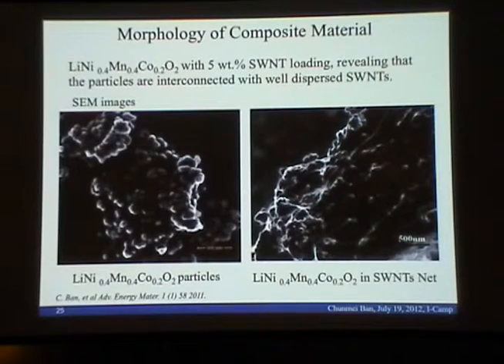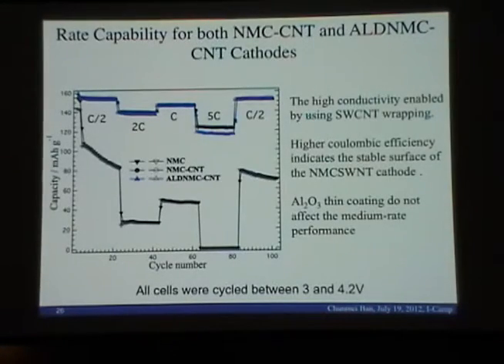This SEM image shows primary particles and finally combined with carbon nanotubes. And those nanotubes are very well dispersed into this particle structure. And finally, we found they have a chemical bonding between those particles and the carbon nanotubes. That further enhances the conductivity, especially the electron transfer on the surface, because the carbon nanotube is on the surface. And so this is the comparison of the effect of this carbon nanotube coating of this material.